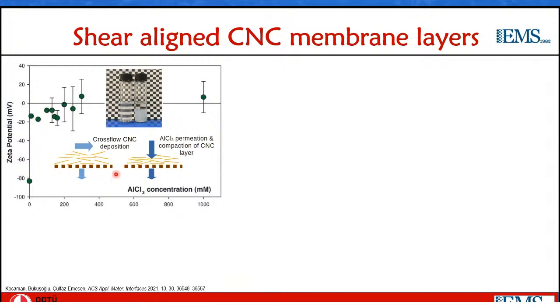What we have been doing until now is to do it by what we can call physical means. So after depositing the cellulose nanocrystals, we permeate a high concentration aluminum chloride solution through the CNC layer. What we make use of here is that an increasing ionic strength would decrease the electrical double layer thickness around these nanocrystals and allow them to become closer to one another, up to a point where attractive forces between the nanocrystals will dominate over electrostatic repulsion. And the ionic strength we can control by the concentration of the salt, as well as the valence of the salt, which is +3 for aluminum here.